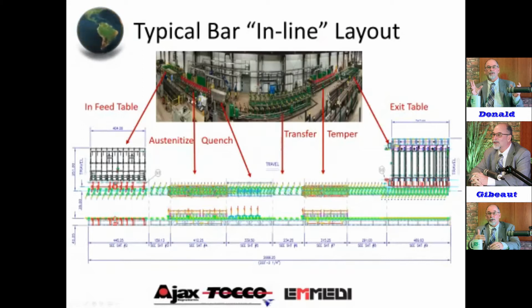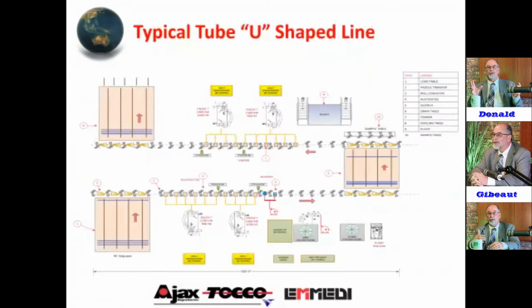So then we come out and we go through the temper section here. This is an inline system just showing the rendition. This transfer table is typically put in right here. Then we go through the temper to adjust it. It comes out hot and gets offloaded onto the cooling bed. And the cooling bed then keeps the rotation and the feed. And typically pipes are on here for hours. And you've got to keep them rotating and keep them feeding, which helps on the straightness.